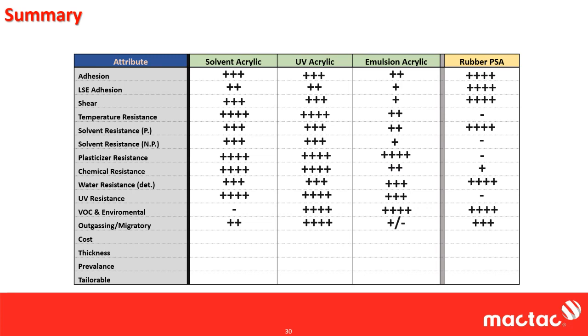So solvent, again, you have VOCs and then you have what's not reacted. What's not reacted could be residual monomer, and that's usually the case there, or any retained solvent, which could be under a VOC. UV acrylic, if there's any monomer that isn't reacted, it's getting stripped off and recycled. Emulsion acrylics actually have a lot of outgassing. So all those other additives like the PVOH, the thickeners, the defoamers, and again, this is kind of the misconception. VOC really focuses on your organic solvents.